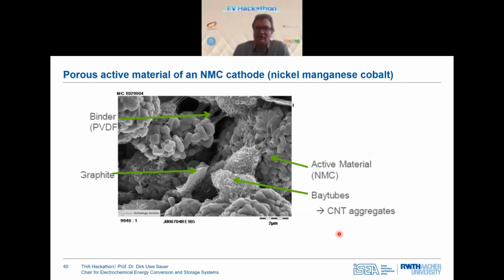And this is just a picture, a view into the active material on a micrometer scale. And you can see here graphite particles, you can see CNTs, so carbon nanotubes, for example, in some batteries, not for storing the energy, but for improving the electrical conductivity of the active material. And here we have the active material. Sorry, the graphite here is also for conducting issues. These are the active materials. NMC stands for nickel, manganese, and cobalt.